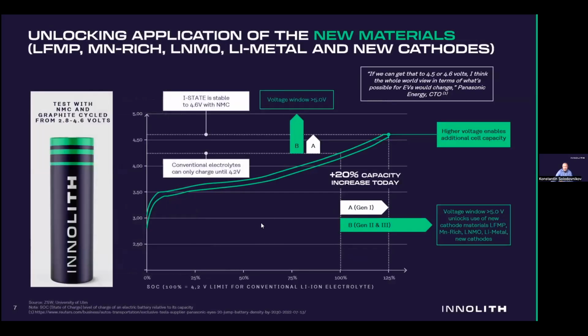The way it works is shown on this chart. You can see a standard charge and discharge curve, and even if you are not familiar with the physics or electrochemistry, it's very simple and shown on the chart. You can see that the lower dash line starts at 4.2 volts, and it shows 100% of capacity in the battery cell that can be achieved by using conventional lithium-ion system.